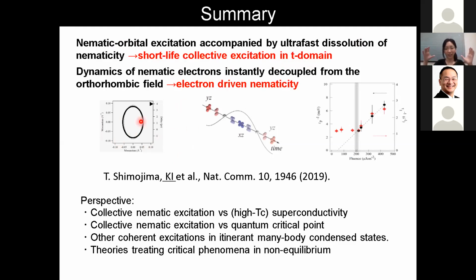Since it appears in a very quick response, we can conclude that this nematic change is driven by the electrons, not the phonons. As a perspective, we are very interested in this collective nematic excitation in relation to superconductivity. At present, we only observe this nematic excitation in the normal state, but it could be closely related to superconductivity. So we want to measure this kind of collective oscillation in the superconducting state. We are now trying to do it at low temperature. And if it's closely related, maybe we can control the superconducting state by using this nematic excitation in the future.